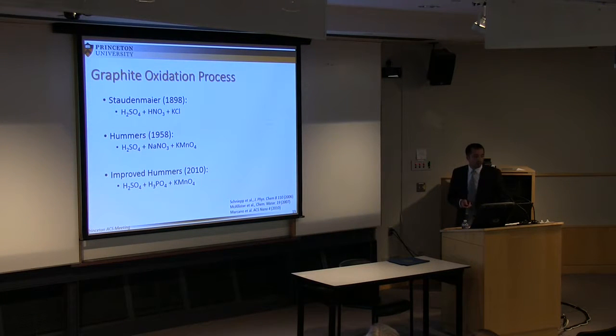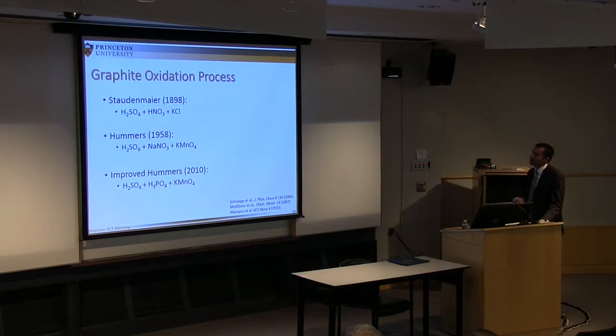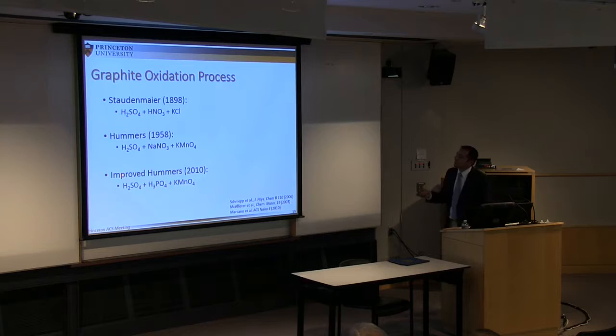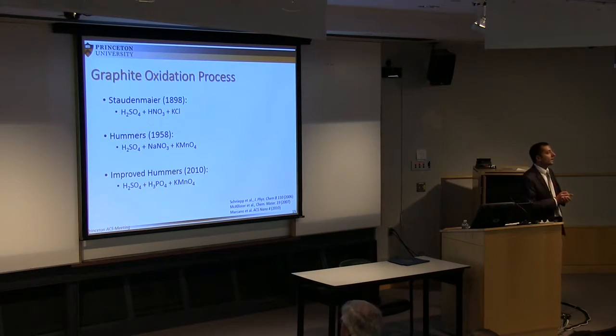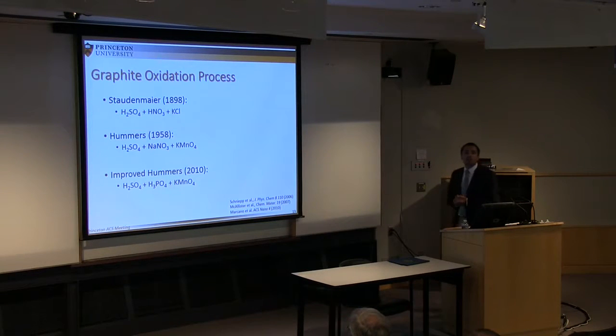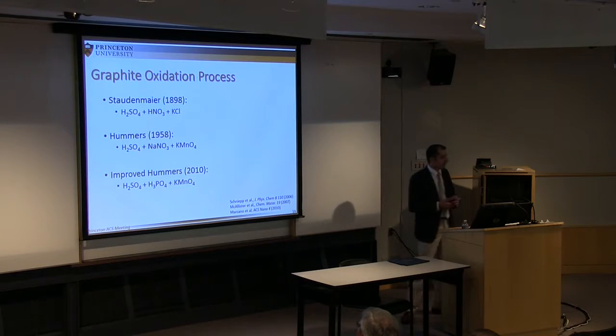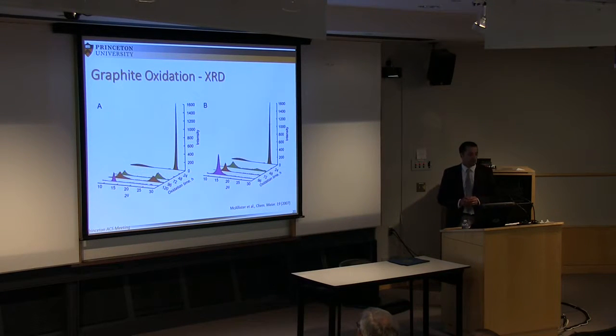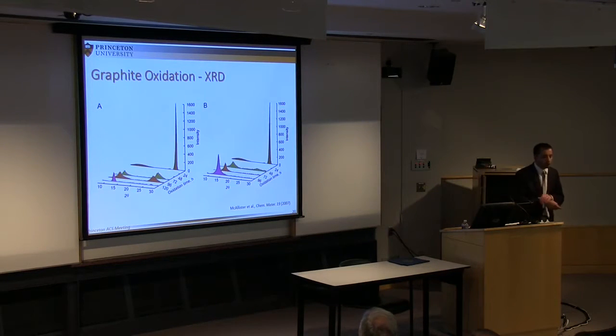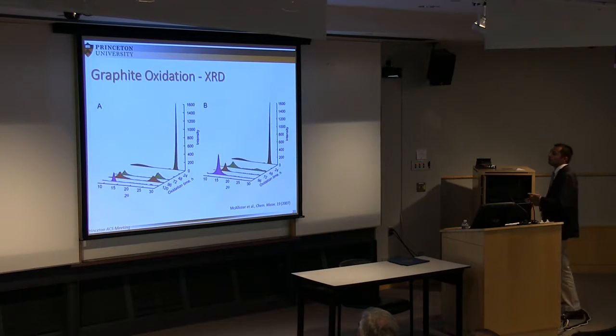So let's discuss a bit more in detail the properties of this oxidation process. Remember we said in 1898, Staudenmaier came up with his synthesis using sulfuric and nitric acid, and potassium chlorate. Hummers suggested to use sodium nitrate and potassium permanganate. And more recently, a group at Rice University further developed that technique by using phosphoric acid and came to have an even better yield in terms of oxidation. However, overall this process is very sensitive. So you have to carefully control your parameters: concentration of your acids, temperatures, durations, etc.